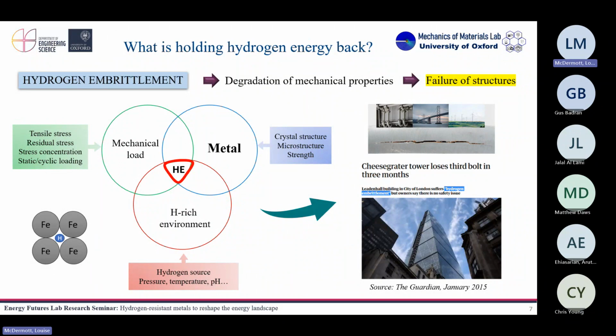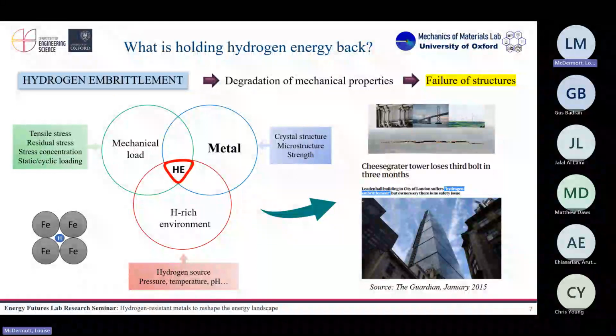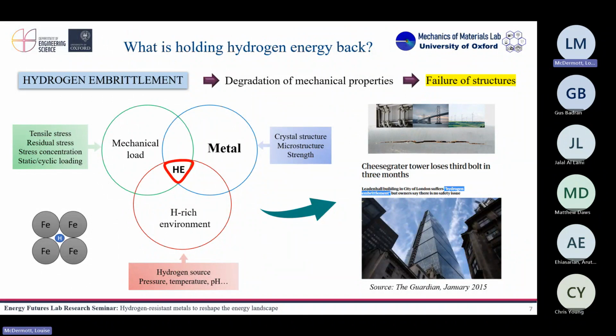But hydrogen embrittlement is a very particular phenomenon, and it only happens if three conditions occur at the same time. You of course need a hydrogen-rich environment, which can be hydrogen gas, but it could also be, for example, any corrosion process, since corrosion produces hydrogen as well. For example, if you have an offshore structure being corroded in the middle of the ocean, you can have hydrogen uptake from the water. Or it can happen during welding, or transport of an acid in a vessel, or whatever situation you can imagine where we have hydrogen. Actually, even from the moisture in the air, we can have hydrogen uptake. So we need a hydrogen-rich environment.